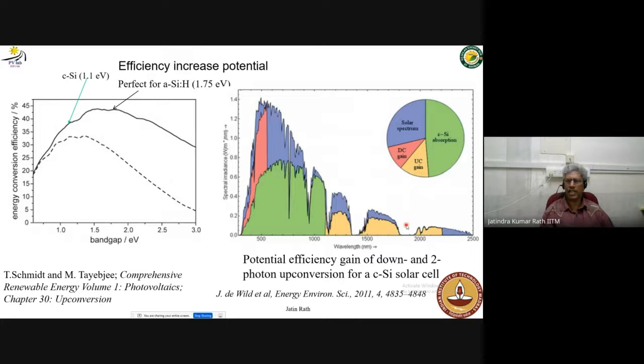Whereas the other way around, I can also take low energy light which is passing through the material, convert it to high energy and utilize it. This is a calculation done for crystalline silicon absorption. The up conversion gain can be around 10%, and the down conversion gain can be this much. So almost 50% increase of the efficiency can be achieved by putting in up conversion and down conversion.